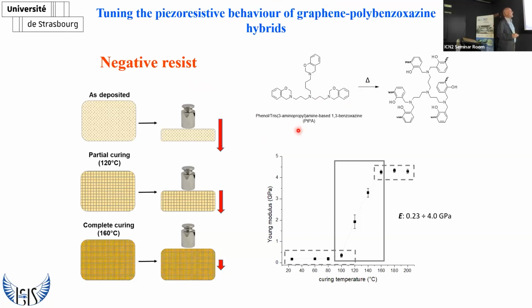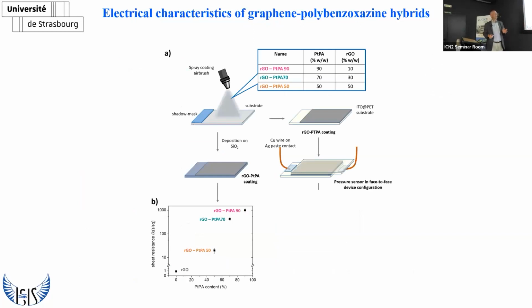Actually, upon cross-linkage, it creates this kind of polymer that can cross-link at higher and higher temperature. So upon curing temperature, we are increasing the degree of cross-link, such that my understanding was the more you cross-link, the more you rigidify the phase. And you can see that the Young modulus is increasing drastically with increase of temperature of our curing. And so we can modulate the mechanical properties.